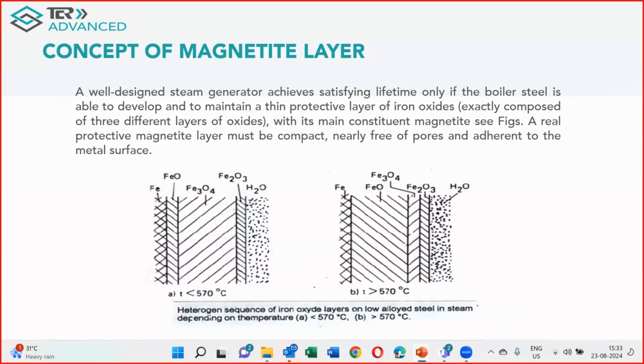So these are examples of how thick scales can be. Sometimes when we analyze boiler tube failures, we observe about 400, 500 micron thickness of the scale. Now this is insane, because it gives you 3 to 4% of extra burning. So whenever the average burning rate increases in your plant, it is important that we remove tubes from a certain sample size. If the operation or combustion is okay, then you need to put in more fuel. Then it's important to analyze the tubes from certain locations. And it also reduces the life of the tube.